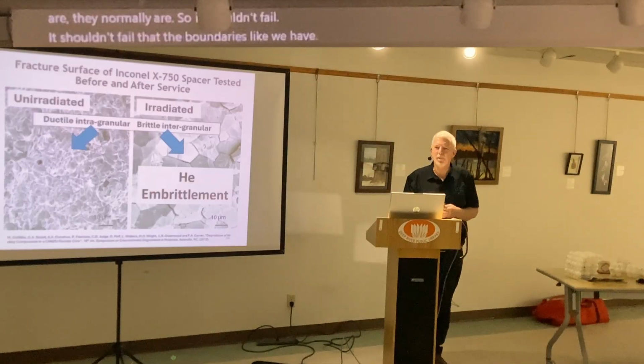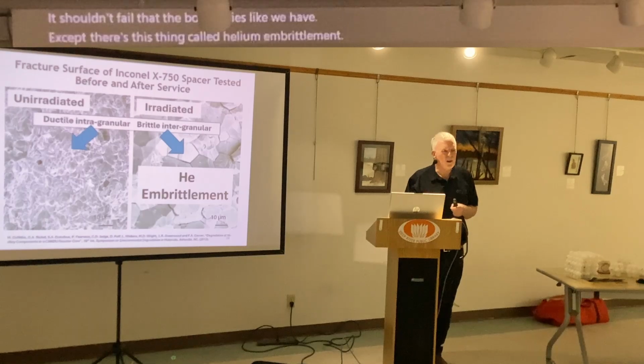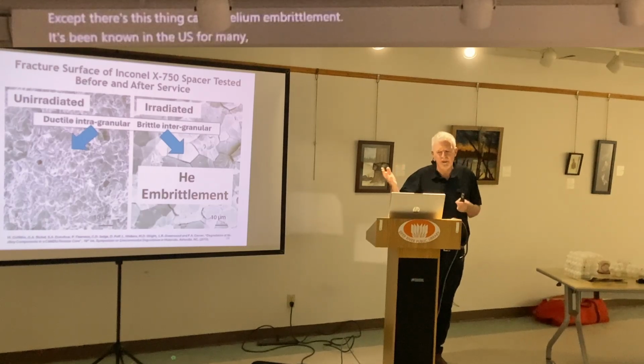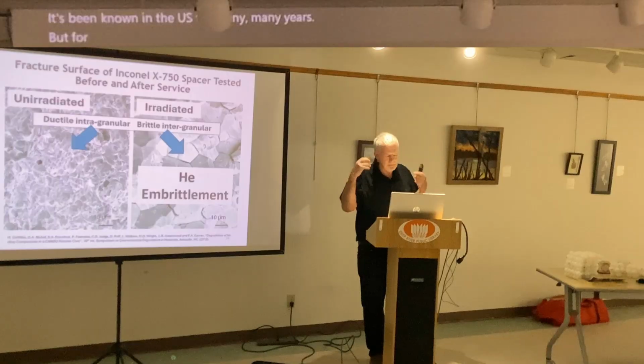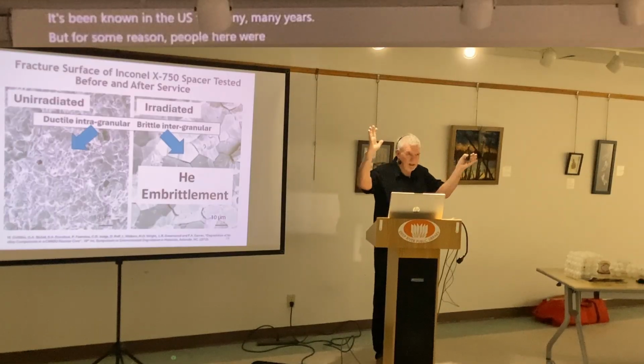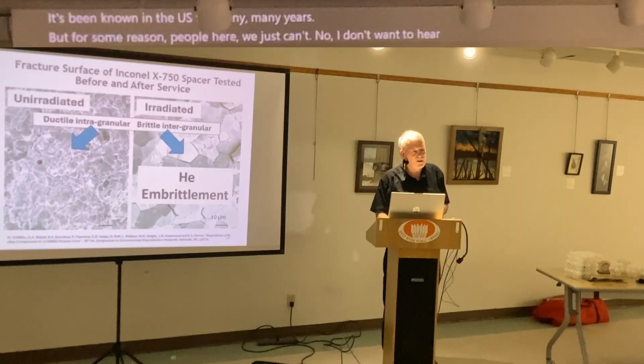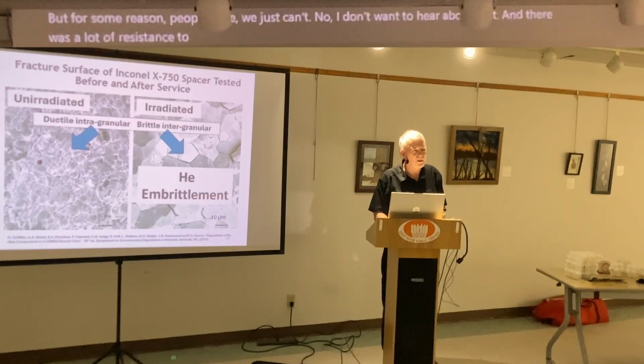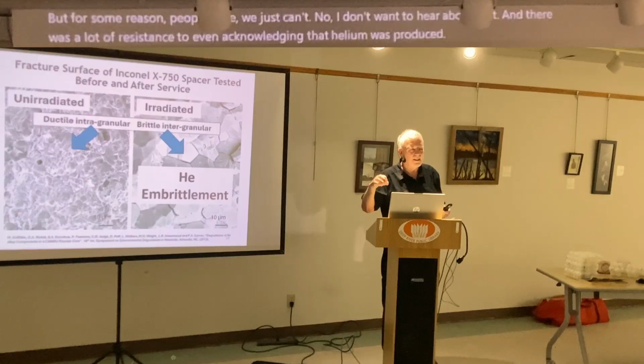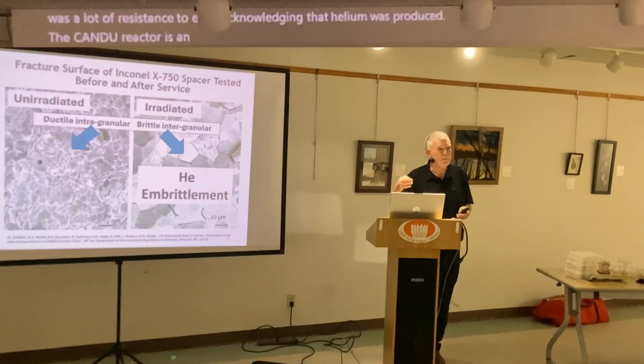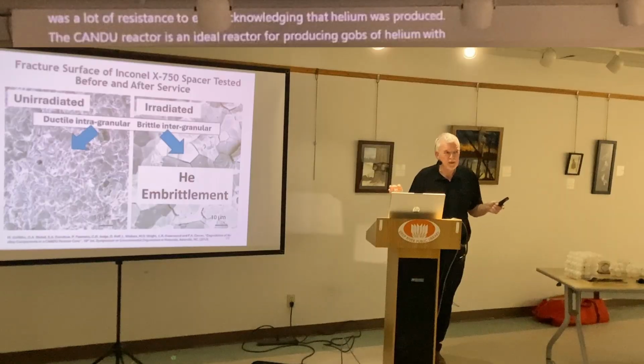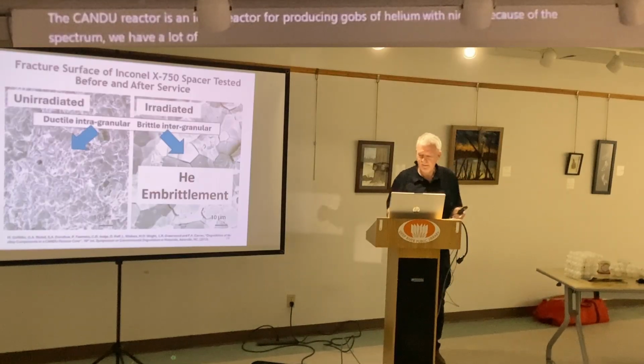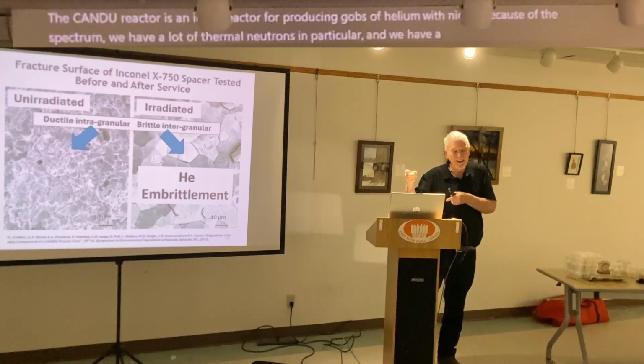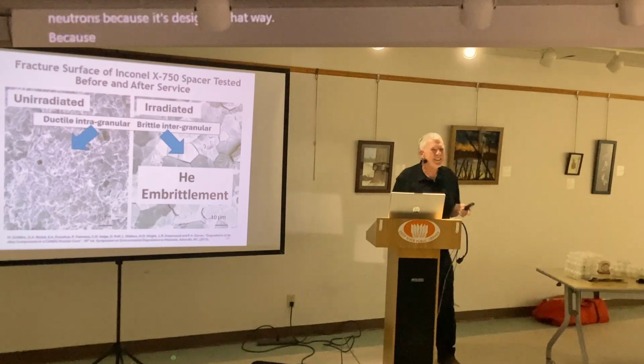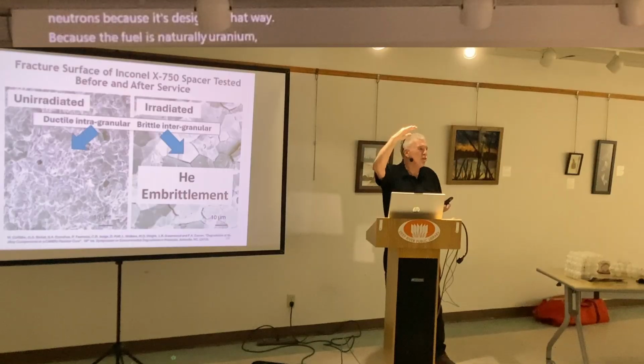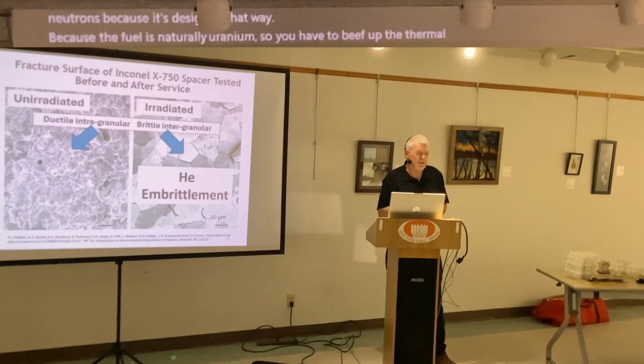Except, there's this thing called helium embrittlement. It's been known in the US for many, many years. But for some reason, people here would just go, well, no, I don't want to hear about that. And there was a lot of resistance to even acknowledging that helium was produced. The CANDU reactor is an ideal reactor for producing gobs of helium with nickel because of the spectrum. We have a lot of thermal neutrons in particular, and we have a lot of thermal neutrons because it's designed that way, because the fuel is natural uranium. So you have to beef up the thermal neutron flux in order to keep the reaction going.